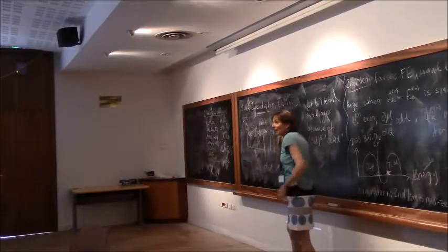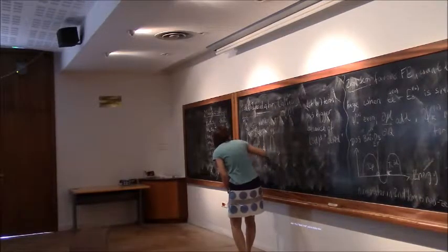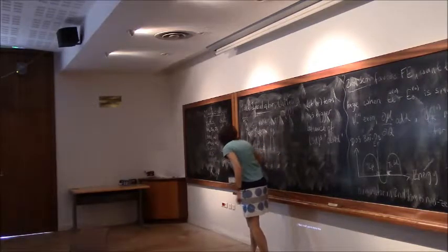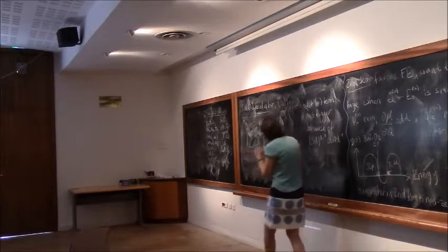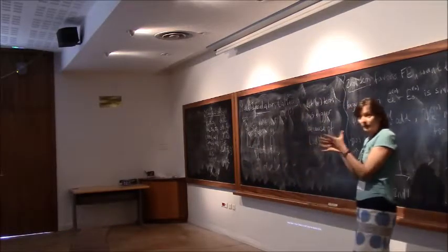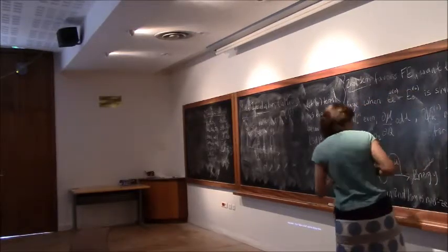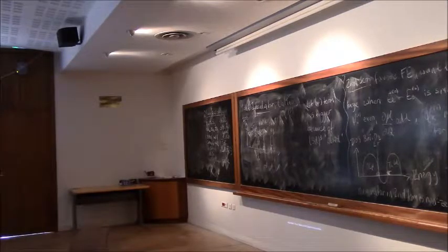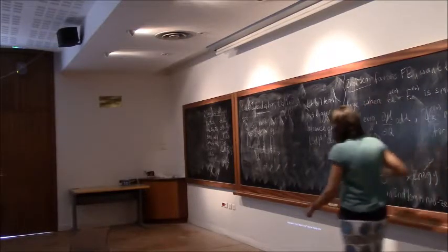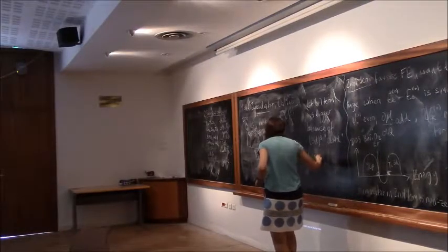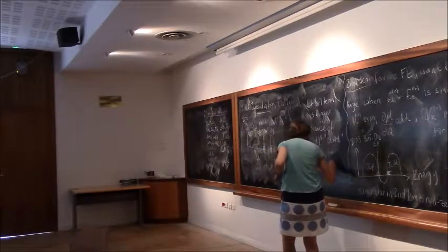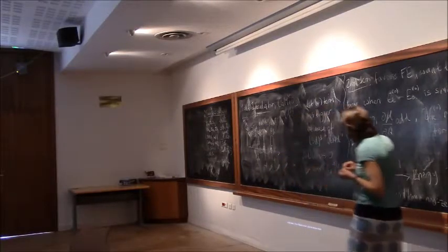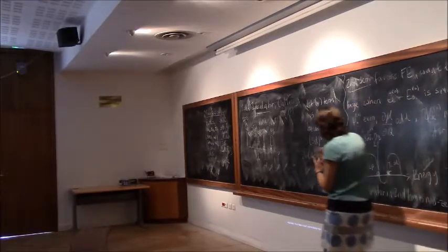Questions? And then the second term. Now I take my electron from the top of the valence band. It has d symmetry, even symmetry, and I put it into the bottom of the eg band, the bottom of the conduction band, which is also a d state with even symmetry. So the numerator of the second term goes to 0, in the case where the denominator is small. So the second term goes to 0 for small energy difference. So calcium manganite is not a ferroelectric.